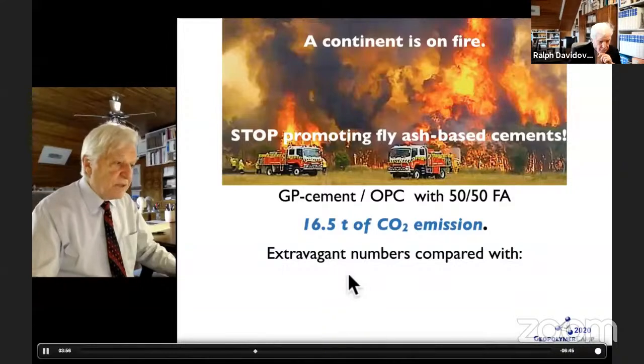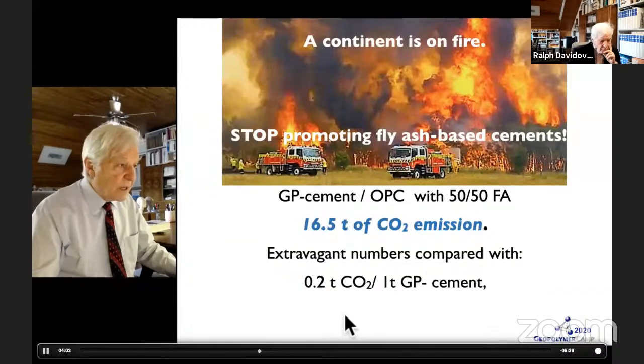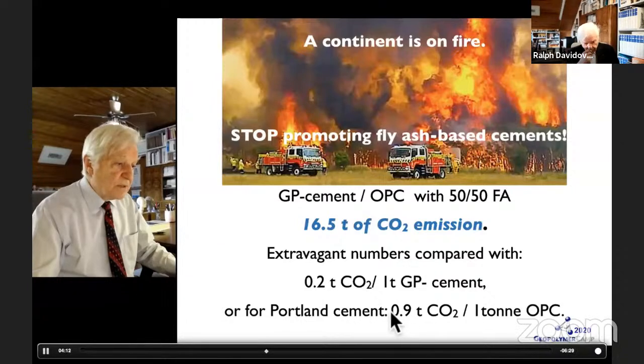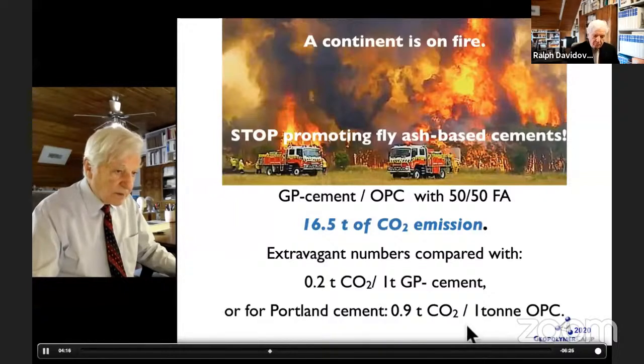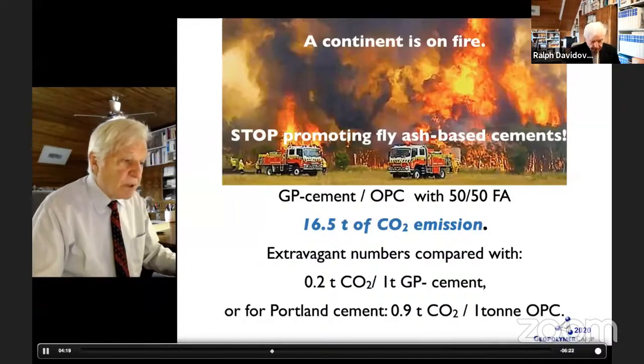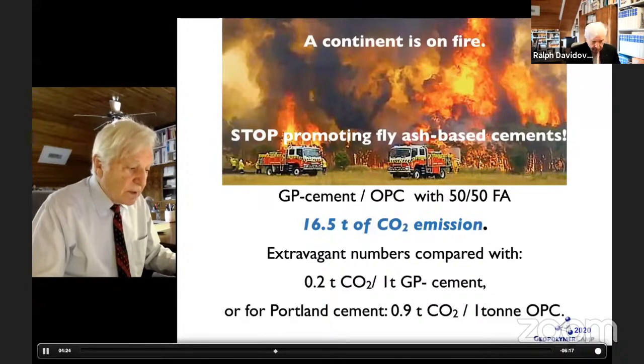This seems to be extravagant numbers. They are extravagant numbers compared with what we have been claiming so far, that is 0.2 tons CO2 for 1 ton of geopolymer cement, 16.5. Or for Portland cement, 0.9 ton of CO2 for 1 ton of ordinary Portland cement. But Portland cement experts and Portland cement industry are not aware of these numbers and are asking for more and more fly ash. Why?